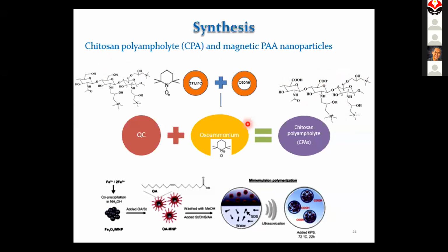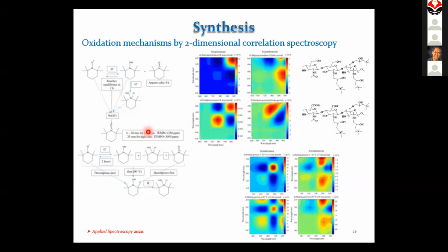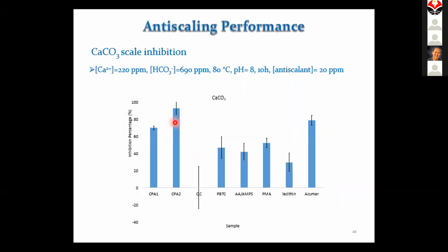So we developed the process to produce this compound. At the same time, we need to know the mechanism very well, so we applied the concept called two-dimensional correlation spectroscopy to study the mechanism of what is going on during the reaction. If we understand it well, we can control the structure of the product very well. As a result, we have the chitosan-based anti-scalant that works very well.